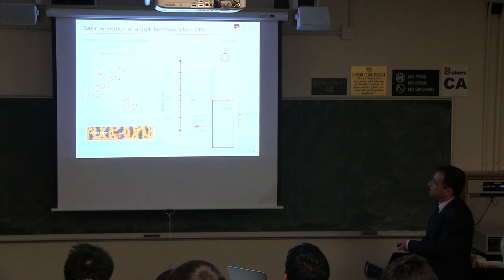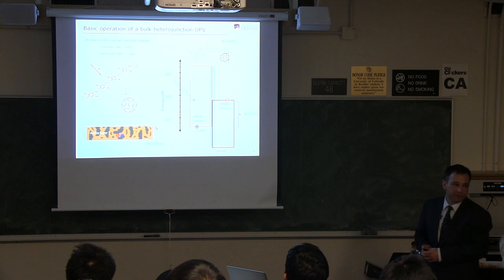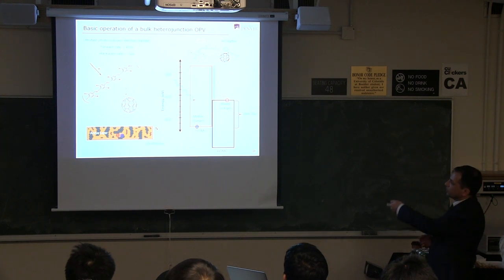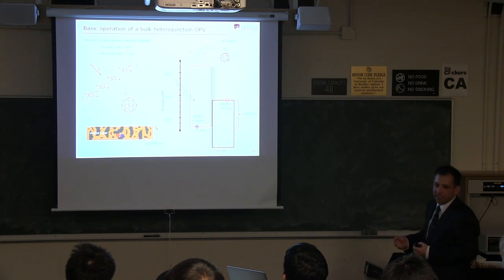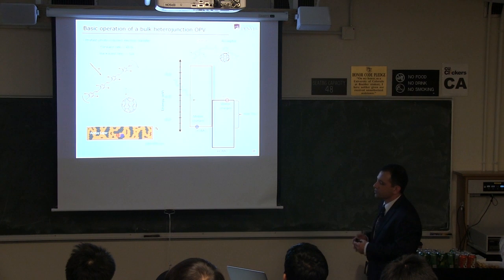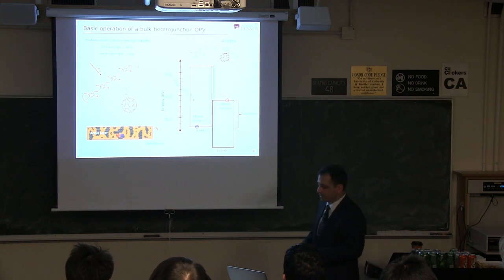By the way, the maximum voltage you get out of the device is this effective band gap. It's kind of a cross band gap between the donor material and the acceptor material. It's another big difference between an organic solar cell and a silicon solar cell, where the band gap is defined by the band gap of the silicon itself.